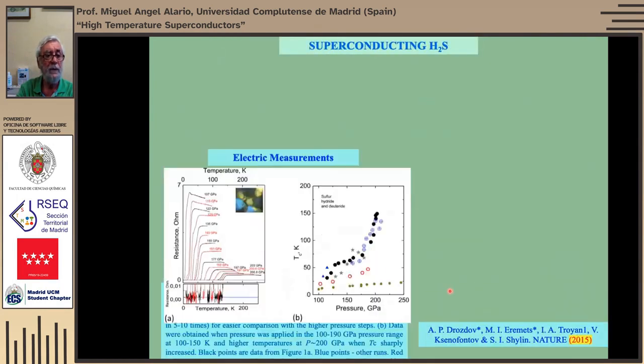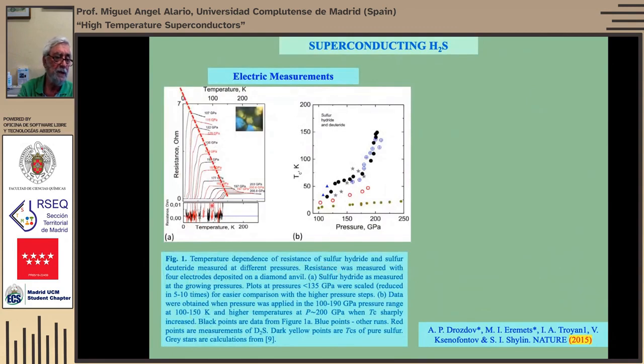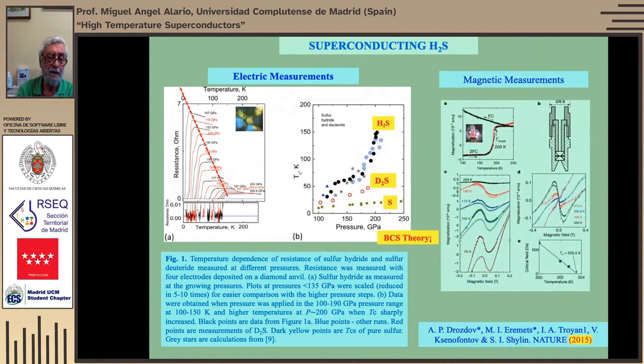And then these are the data. You see that when you increase the pressure, you are increasing the critical temperature. Here, temperature as a function of pressure. And the interesting thing again is that this is with deuterium, so there is an isotope effect. So it means that this follows the Bardeen-Cooper-Schrieffer model. And then these are the magnetic measurements. Very difficult to do magnetic measurements at these very high pressures.